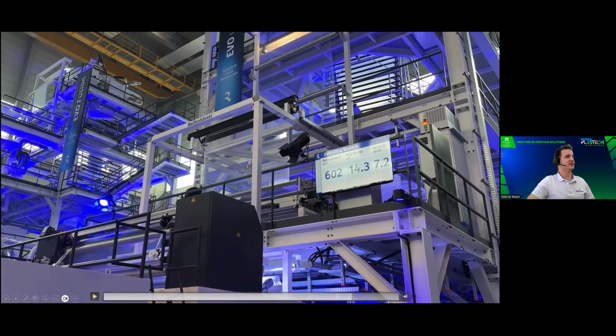Then on the third line, you see our Evo Ultra Stretch. This is our MDO line. Our MDO has here a unique position inside the takeoff unit. So we are stretching between the nip and the turner pass, which is also a patent. And here we achieve a stretching ratio of over 7. So we extrude with 100 micron film and stretch it down to 14 microns, what you can see here, and achieve this very unique value that's outstanding, and also helps you to come closer and be more competitive to PET, where it will be replaced for.